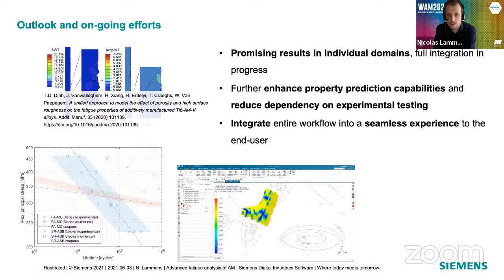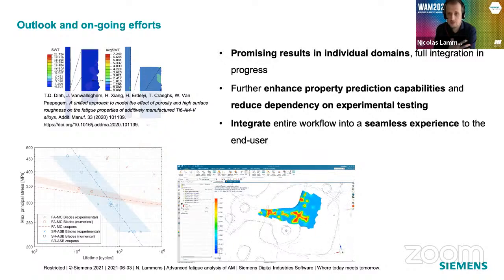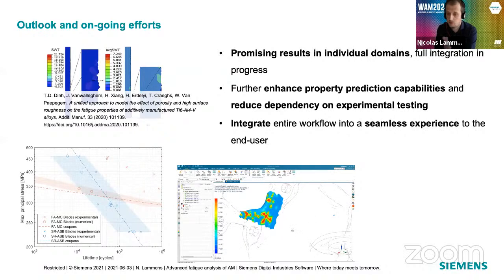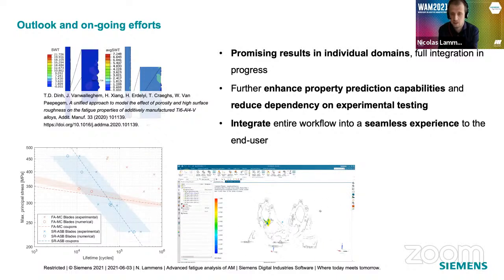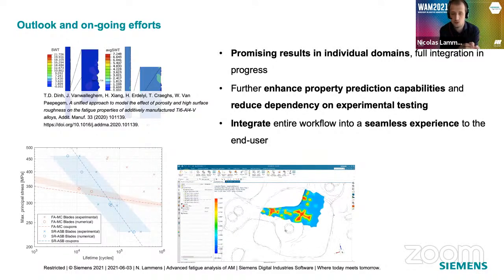What we have seen so far is that we get very promising results in several of the individual domains. For example, surface roughness prediction, porosity prediction, fatigue life prediction, but integrating and interfacing all of these individual domains together is still a work in progress. On top of that, we want to further enhance the property prediction capabilities. So we want to be able to predict even more properties. And we also want to reduce the dependency on experimental testing. As I said, we want to ideally come to a point where we only do the bare minimum of testing and all the rest comes from simulation.